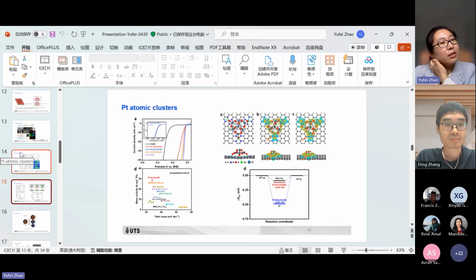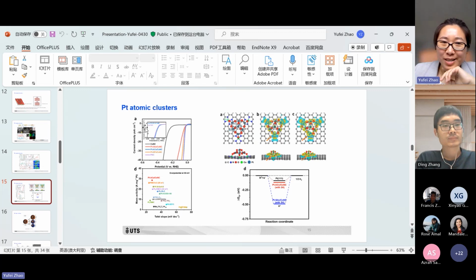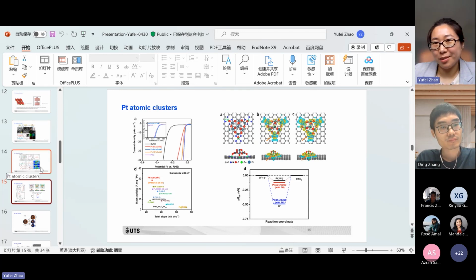But for the HER side, I haven't talked about the OER here. For the OER side, we have tried a single atom, but the OER is a 4-electron process. So for the OER side, we are still working on oxide materials, ruthenium oxide, not single atoms. For single atoms, they are randomly distributed, and it's hard for these 4-electron systems. For the HER, it's 2-electron transfer, so it's much better to utilize atomic clusters or single atoms.